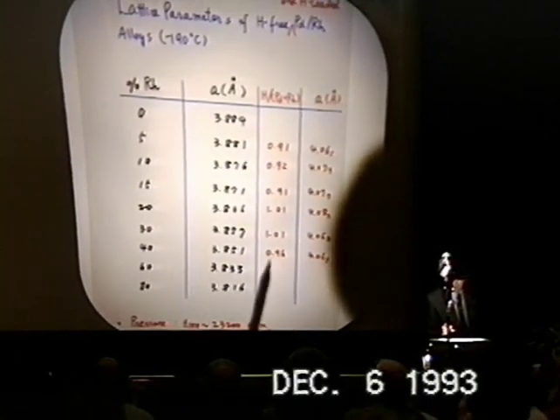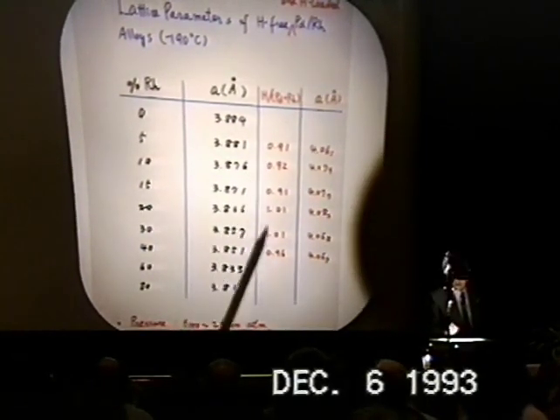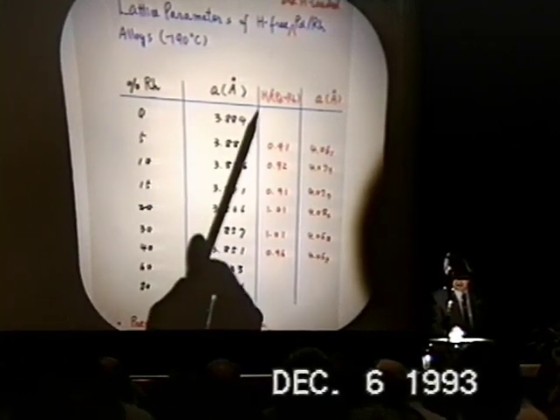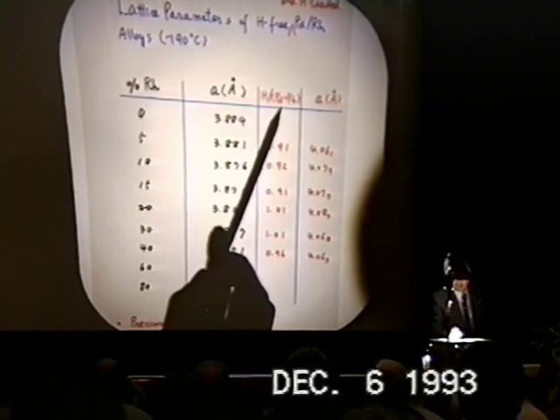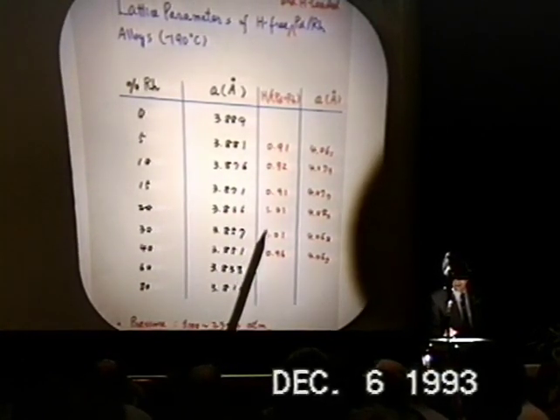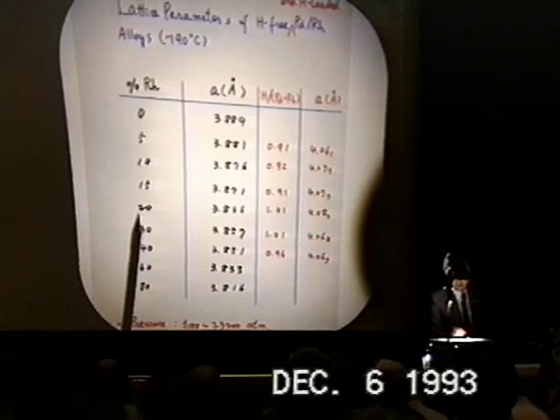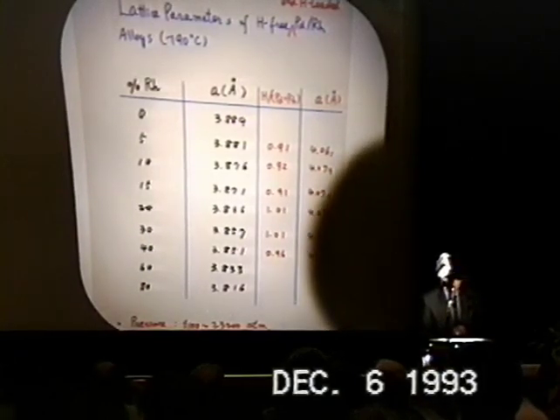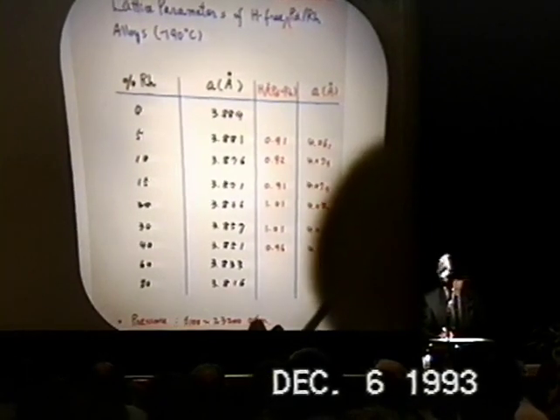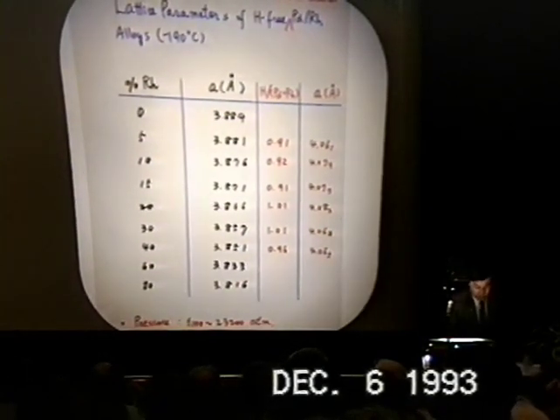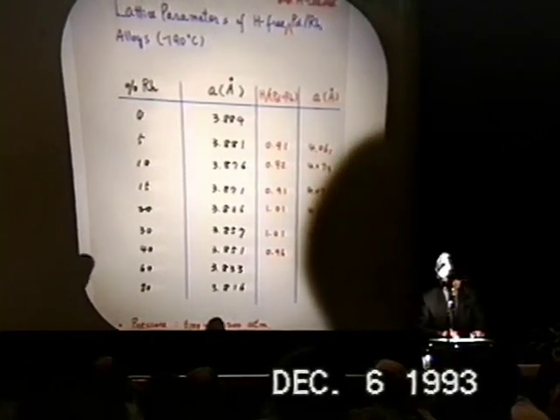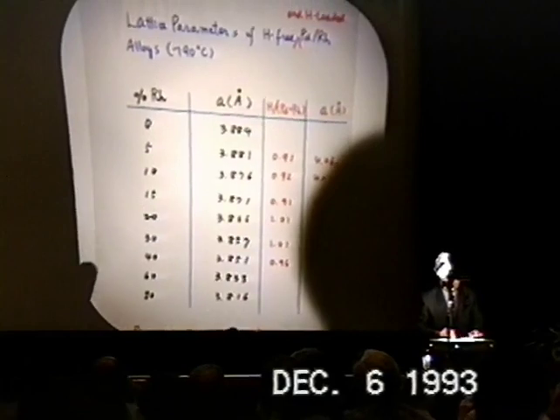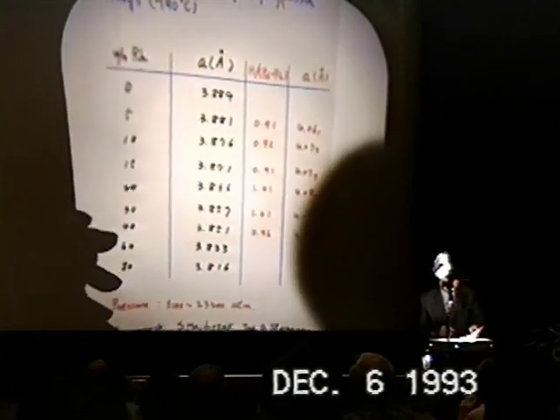And then they reported that the hydrogen to metal ratio, expressed by H/M, is almost 1 at the content of 20% or 30% of rhodium palladium alloys. So we ordered these palladium rhodium alloys from Johnson Matthey.